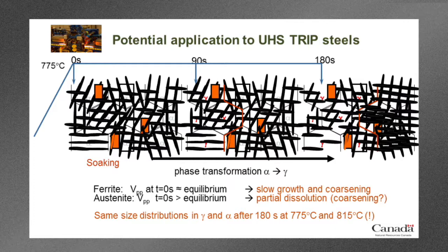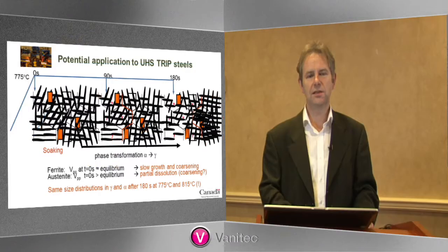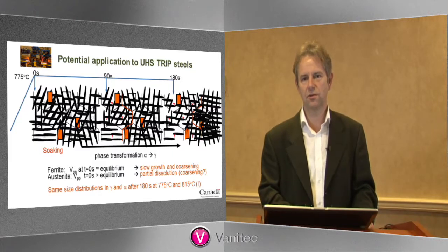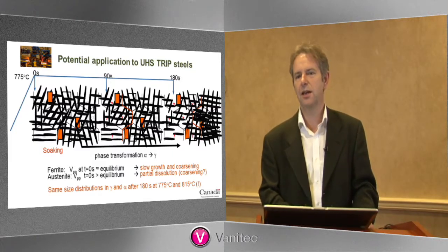Now, we know after 90 seconds of holding, we've started to form quite a lot of austenite. In fact, we're actually almost at the equilibrium fraction of austenite formation, just a bit less than that. So I've indicated this here by this orange line. This is supposed to be a grain boundary between ferrite and the new austenite that we formed during this annealing. Inside the austenite, what's happened is that these vanadium carbonitride precipitates are starting to dissolve, especially the smallest ones. The smallest ones dissolve first via the Gibbs-Thomson effect. Inside the ferrite, in contrast, it's completely different. The precipitates are not dissolving, they're actually growing, and some of them will be coarsening as well. So we can see that these small ones disappear in the austenite, and the smaller ones will tend to grow in the ferrite.